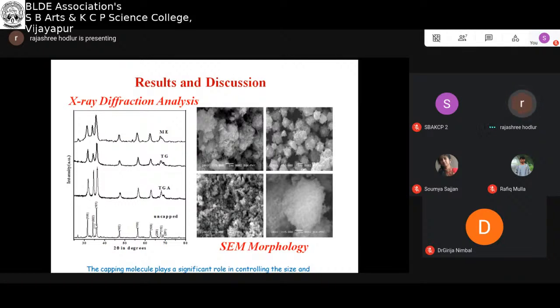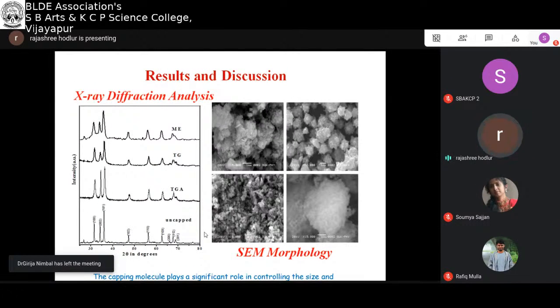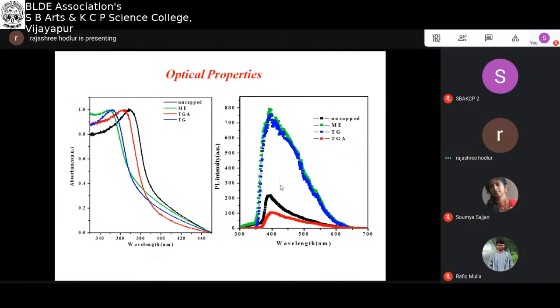This XRD pattern clearly reveals how the particle size can be tuned. This is the uncapped, and by introducing thiols, you can see how the particle size is tuned. In order to see the morphology, we carried out SEM analysis, and we observed that the capping molecules play a significant role in controlling not only the size but also the shape of the nanoparticles. As we know, the bulk band gap of zinc oxide is around 3.3 electron volt, and its corresponding wavelength lies around 375 nanometer. When the UV absorption measurements were carried out, you can see the blue shift, and this clearly shows that the particle size is reduced and the band gap also increased significantly.